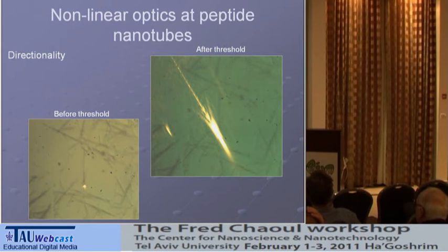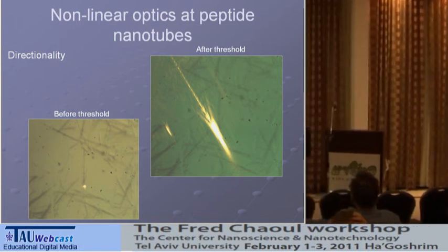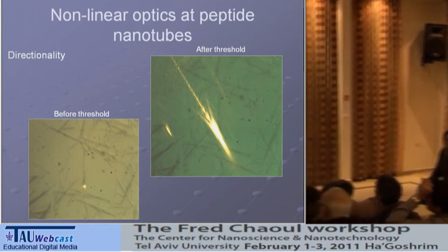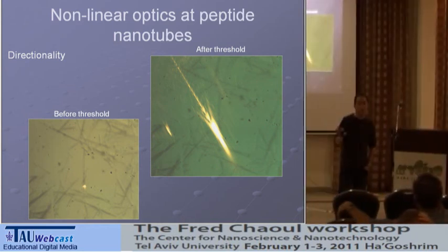It's reversible, but the problem that we see is that sometimes to get this, we are burning the sample because we need a high intensity laser. So this is the reason that we cannot see it in many cases, only in very rare cases, because usually it burns in this state. But is it reversible? The answer is yes, in the cases where it doesn't burn.